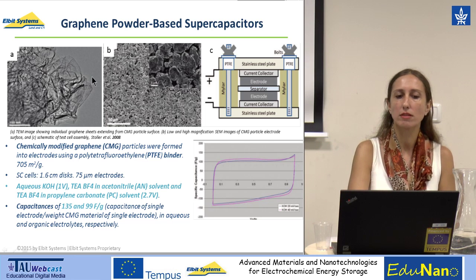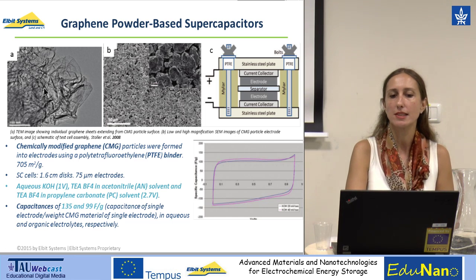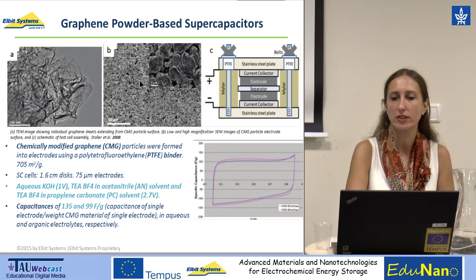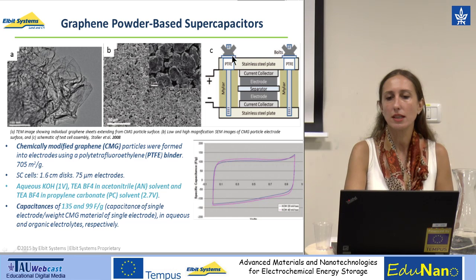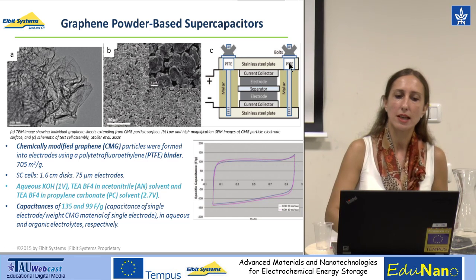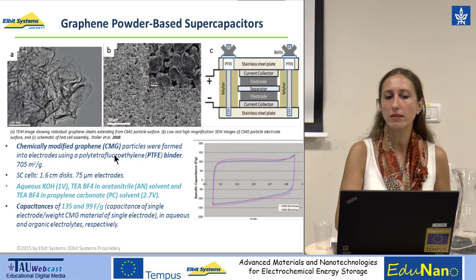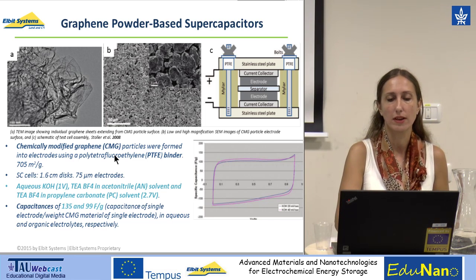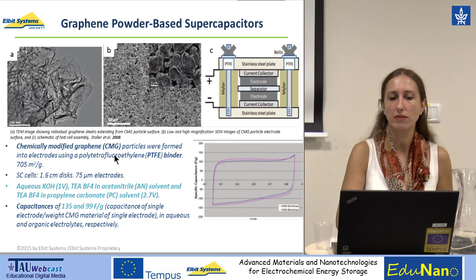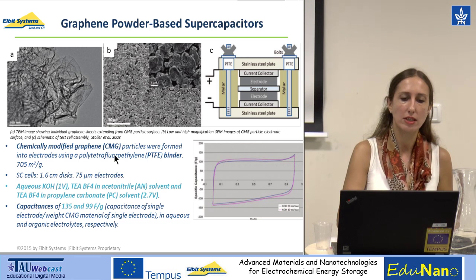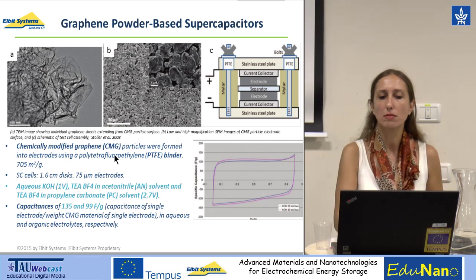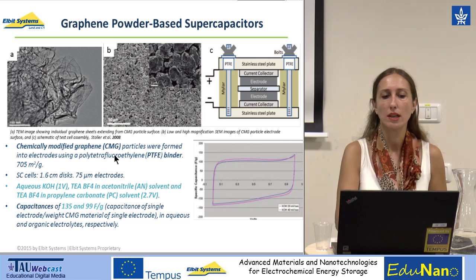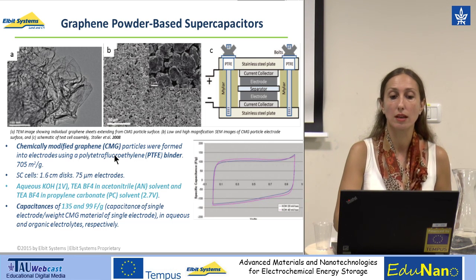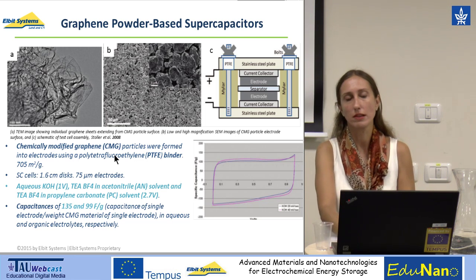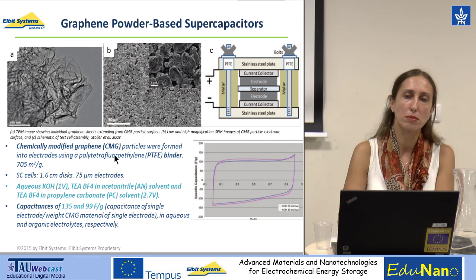Here you have the transmission electron microscope images showing the individual graphene sheets extending from the CMG particle surface, and in B you have low and high modification of scanning electron microscopy images of the CMG particle electrode surface. At C, as I said, the configuration of the cell. These supercapacitor cells were in the size of 1.6 centimeter discs with an electrode thickness of 75 micrometer. They were tested in a variety of electrolytes. First of all, an aqueous alkaline KOH electrolyte having a cell voltage of 1 volt. They were also tested in acetonitrile solvent and as well as in the propylene carbonate solvent. Both those solvents have, as we discussed, a higher cell voltage of 2.7 volt.